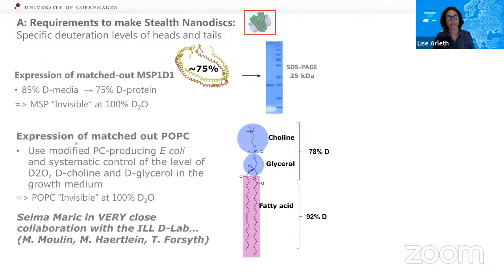And then another thing that we did was to express match-out deuterated POPC. So the idea here was that we used an E. coli strain that was PC producing, and then we systematically controlled the level of D2O and deuterated glycerol in the growth medium. And then we could deuterate it 78% in the head groups and 92% in the tails.